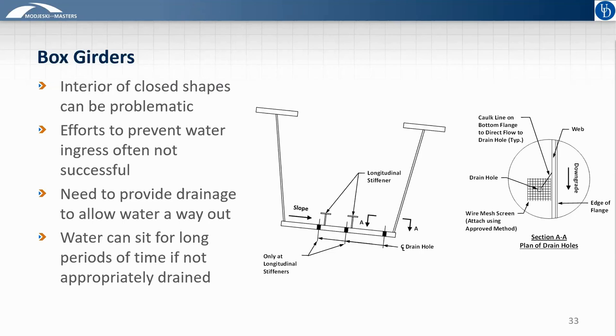So looking at slopes, again, put drainage holes at the low points. So that's what's shown on the left here. If you have bottom stiffeners, you might need drainage holes for each stiffener, and then one at the very low point of the cross section. Obviously, you don't want birds and small mammals getting in your box girder, so you want to screen those and think about using caulk and other drainage directivity devices there to keep the flow going to the drain holes and not collecting. If you don't do this, water can sit for long periods of time, and it is not uncommon to see closed shapes that haven't been detailed appropriately having significant corrosion where water has ponded.